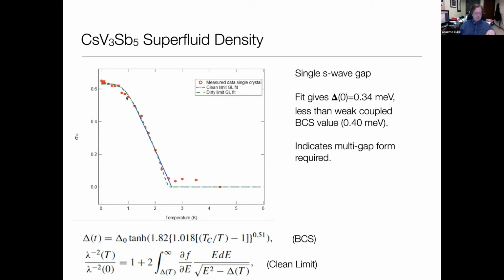It's most likely that you see a temperature dependence coming in at low temperature here, which is not there in the BCS state, which should be flat. So we're now extending our analysis to have an S wave gap for the primary gap, and adding in a second D wave gap, which will be the leading term on that. So right now it looks like we have multi-gap superconductivity, much like we do, for example, in magnesium diboride, and one of the gaps may in fact be a non-S wave.